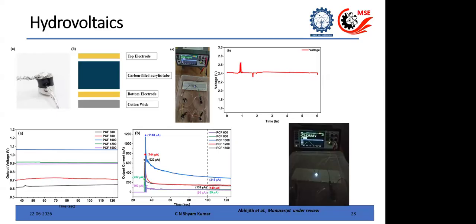So here in this case, you have a perfect microstructure, morphology, as well as the chemistry in the carbon to have higher performance, higher voltage and current. So here the trend is something different. So you can tune your material. Actually, we could again improve this by functionalizing the carbon. I haven't shown this. So you functionalize the carbon again, and then the output has improved drastically.